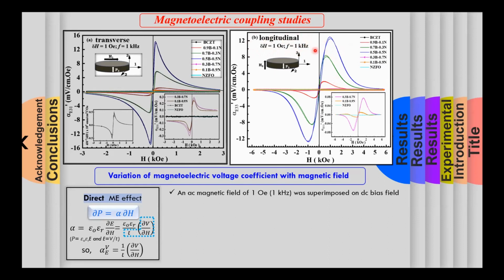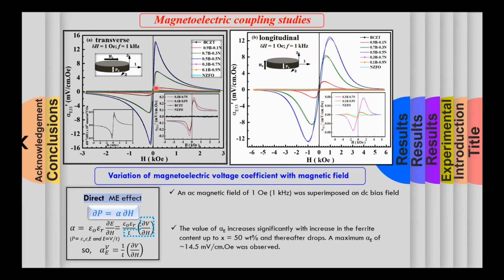As far as the dependence on the ferrite content is concerned, it was observed that the value of the magnetoelectric response increases significantly with increasing weight fraction of the nickel zinc ferrite, and the maximum was obtained for the 50-50 composite, that is with 50 weight percentage of nickel zinc ferrite.